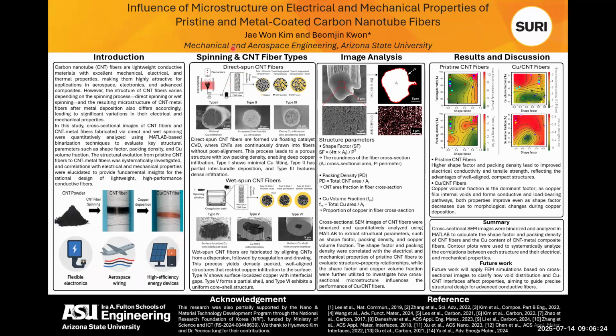In this study, two representative spinning methods were used to fabricate CNT fiber: direct spinning and wet spinning. Direct spinning is a process where CNTs are continuously spun into the fiber form during catalyst assisted CVD. Wet spinning involves dispersing CNTs in solution, followed by alignment and drawing in a coagulation bath.